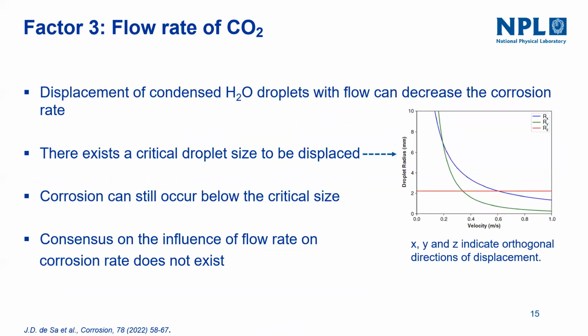So what could be the positive impact? There is a hypothesis mentioning the displacement of condensed water droplets with flow, decreasing the corrosion rate. If you have water droplets in the CO2 pipeline, the flow will displace the water droplets, so they don't settle on the steel pipeline, and corrosion cannot occur. These researchers have done modeling calculations on the critical size for a droplet to be displaced. They found there is a critical size, so corrosion can still occur if the droplets are below the critical size.